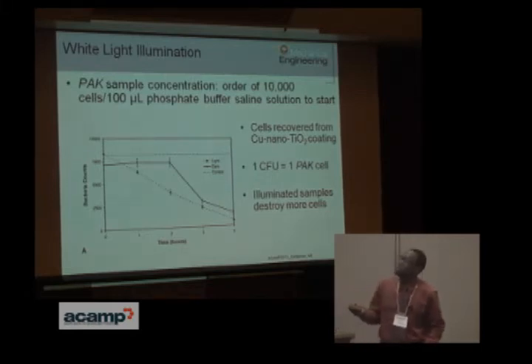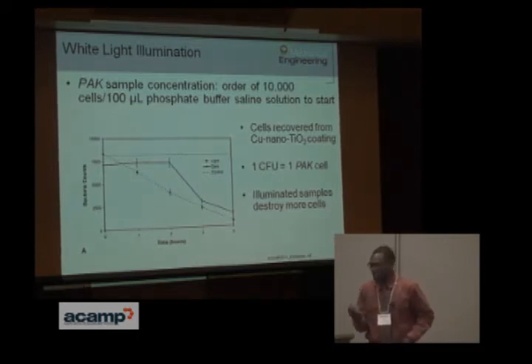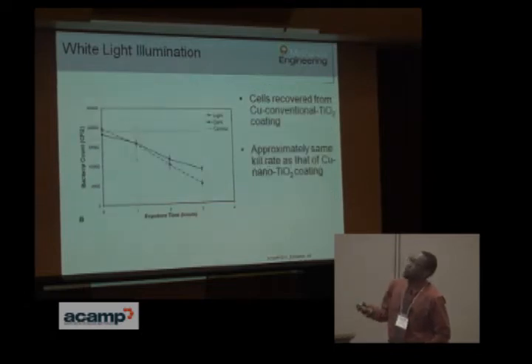I should underline also that the copper is also killing bacteria in this case, and that's why in the dark chamber the number of cells also decreases nicely, because I am getting some antibacterial activity. But one should note, I'm only working with 5% of copper. So that's just a note that I want to bring to light. We did go ahead and work with conventional, regular TiO2 mixed with copper and made a coating out of that. And you can see also, again, significant decrease in the amount of cells that we have.